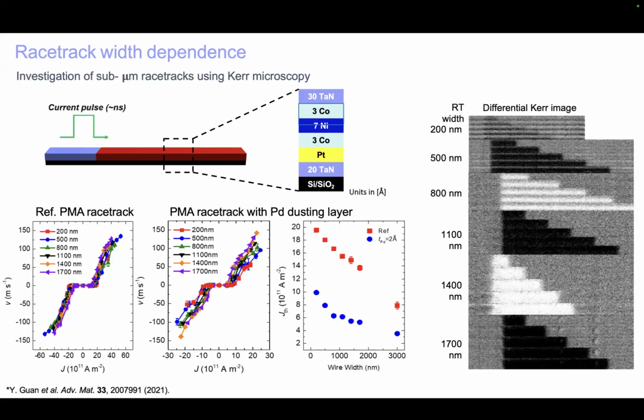And the reason why that could have been a problem is that the edges of the racetrack always have some roughness, because during the lithographic processing you always create some line edge roughness. And this could lead to pinning of the domain walls. However, we found that although the threshold current to move the domain wall initially increases a little bit, it only increases by about a factor of 2 as we shrink the width of the racetrack. You can see here from 1700 all the way down to 200 nanometers.